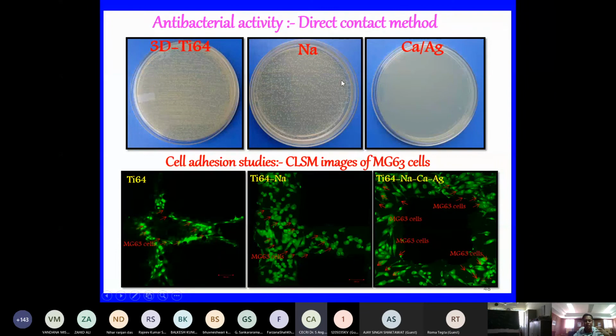And here also we have done this using a 3D printed porous scaffold. We try to use this for antibacterial activity as well as cell adhesion studies of bone cells, MG63 osteosarcoma cell lines, and we found we can optimize the silver concentration that can have antibacterial activity, because you can see in the upper image there is an optimum condition I have shown here in the slide. There are no bacteria cells available, but bone cells are live,